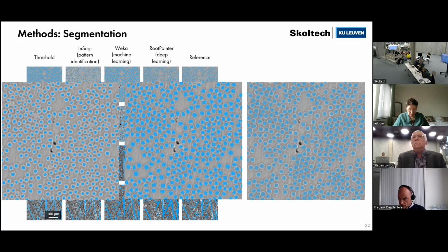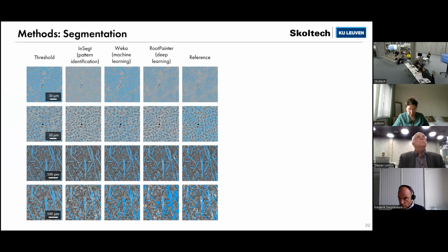But with short fiber composites, I will show it. For example, in these examples, this is a much more difficult case, because it is not as easy to create such algorithms that will create our parametric model with all the fibers located as close to each other as in real life, which produces a high fiber volume fraction. For example, with the existing algorithm, the random adsorption algorithm, it's possible to achieve only approximately 30% volume fraction of short fiber composites.